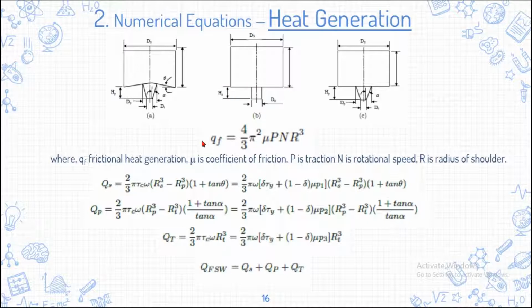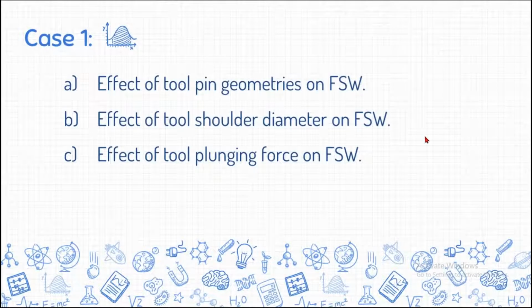Qs is the heat generated at the shoulder. This is the equation to find out the amount of heat. And for the tool pin, this is the equation, and for the tip of the friction stir welding tool, this is the equation to find out the amount of heat generated over these regions. The sum of all these, Qs, Qp, Qt, for the shoulder, pin, and tip of the tool pin, will give you the total heat generated in the friction stir welding process. These equations should be incorporated in the input values.